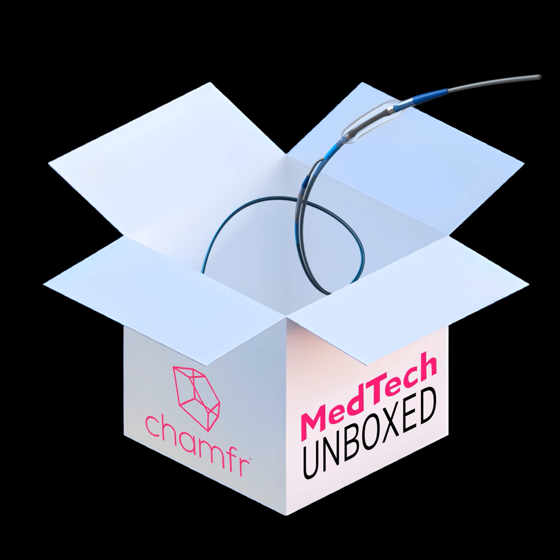With thermoplastics, which we will go over later on, like the Dynaflex new EverGlide Plus or the SUS new PFX, other extruded products, if it's a thermal extrusion, there's a limitation on how thin it can go, and a lot of the thermoplastics today cannot be dip coated or film cast. With PTFE, it's possible to film cast it. I think that's one of the reasons, and it also has a very long biocompatibility history. Everybody knows it. FDA knows it. Everybody uses PTFE in their application. So from a history standpoint, coefficient of friction, and thin wall, that's why PTFE remained the gold standard.